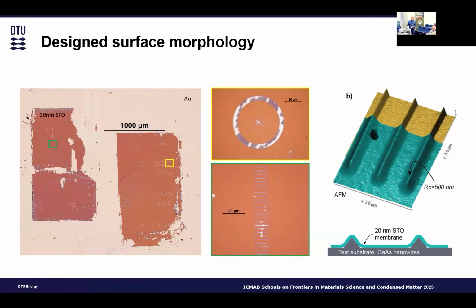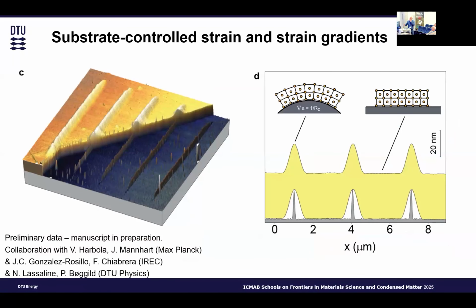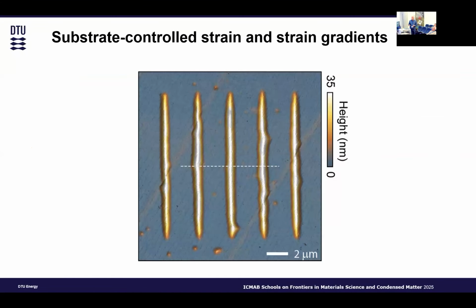Okay. So we put a membrane on top of these structures, and we looked at how the structure conforms. This is just an illustration from the AFM of how the structure conforms on these nanowires. So this is a real picture after we measured it. We believe that of course there is some strain gradient at the tip here, and there is no gradient here. The whole idea was to create a strain gradient in a place where we can measure the changes of the material. If we take STO, for example, this is what we did. We took STO and wanted to see whether we can induce ferroelectricity due to the flexoelectricity. That was the original motivation.